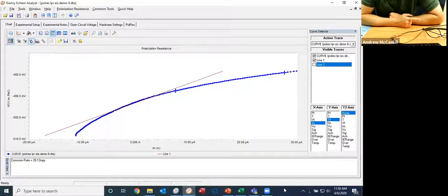And if you think about what you do with EIS, once you get to the DC side of an impedance measurement, essentially you're applying the same perturbation as you were with the LPR experiment. Me only going down to 1 Hertz certainly isn't polarizing the surface as long as the LPR experiment was.